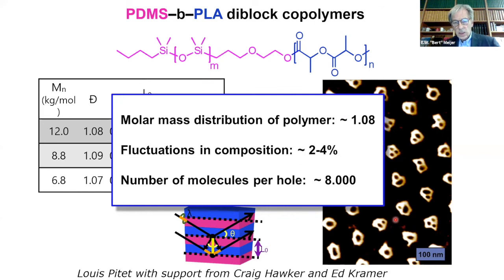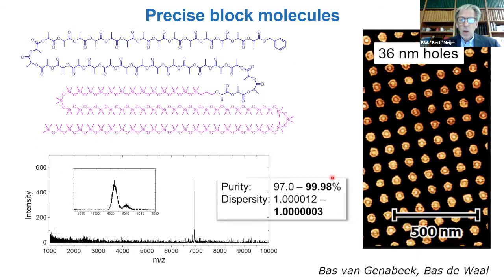Then we did a calculation. And what turns out, in such a hole, you only have 8,000 molecules. The molar mass distribution is 1.08. The fluctuation in composition is 2 to 4%. And as a result, there's not a single hole that has the same composition of molecules. And as we know from work from Craig Hawker and Ed Kramer, especially in confined space, it is very sensitive to the composition. So what we then decided was to synthesize precise block molecules.